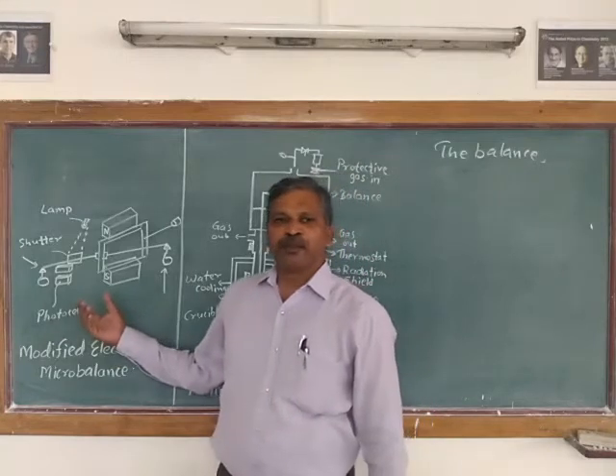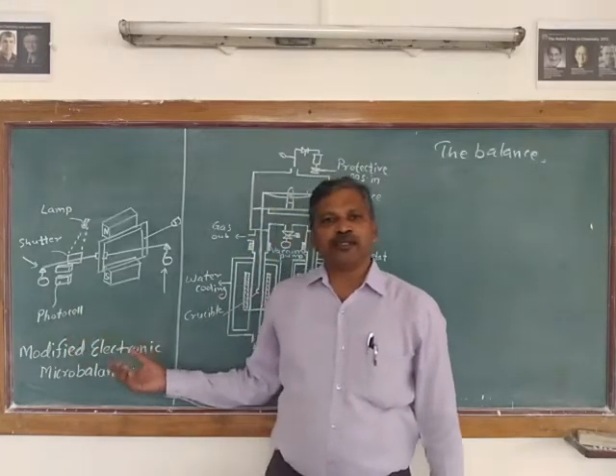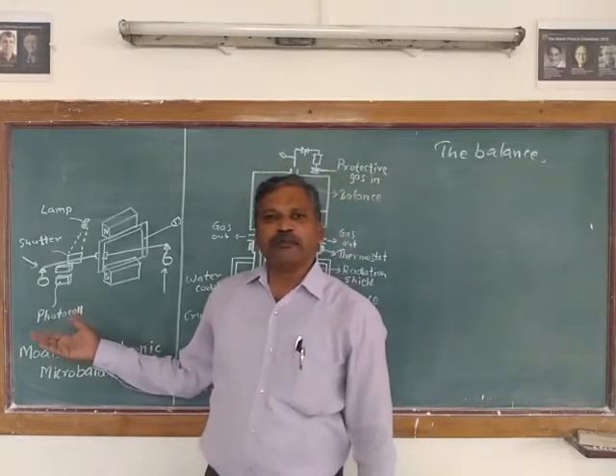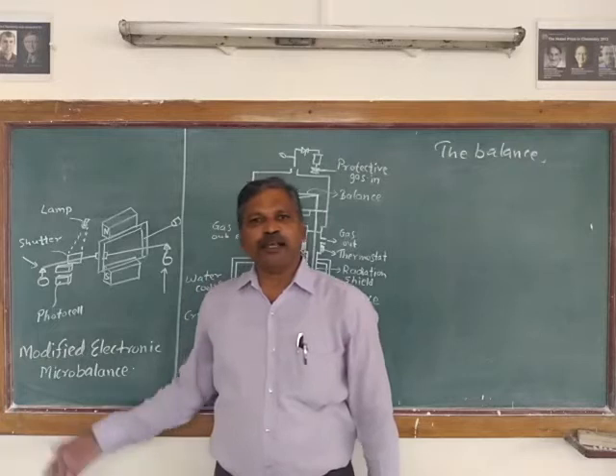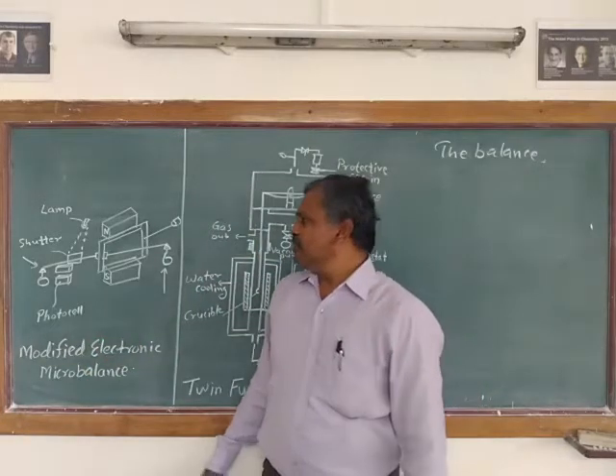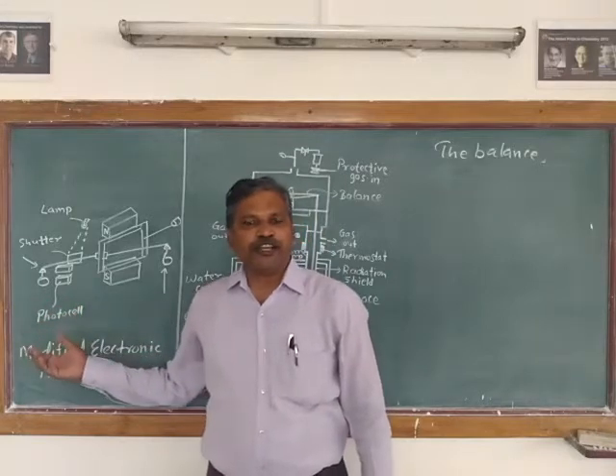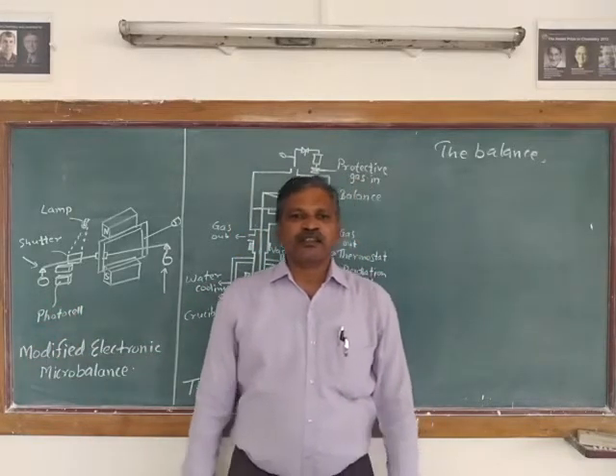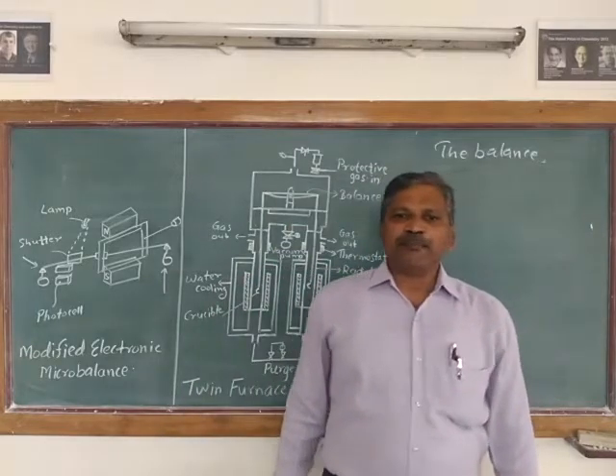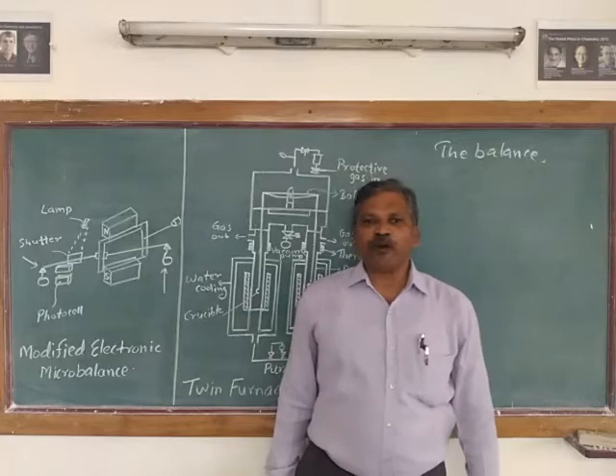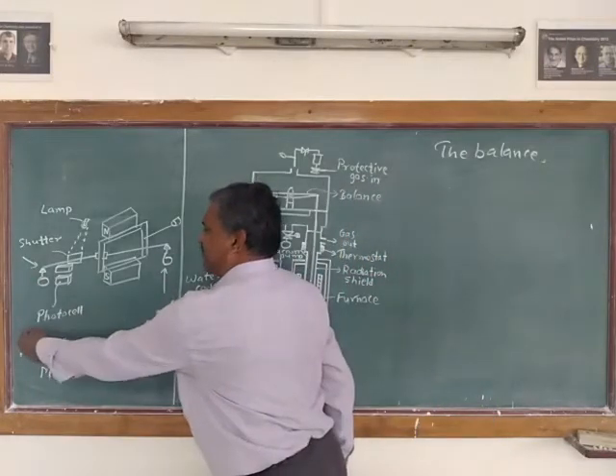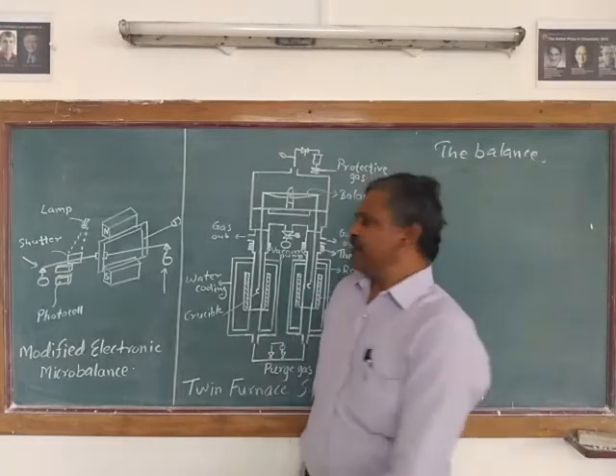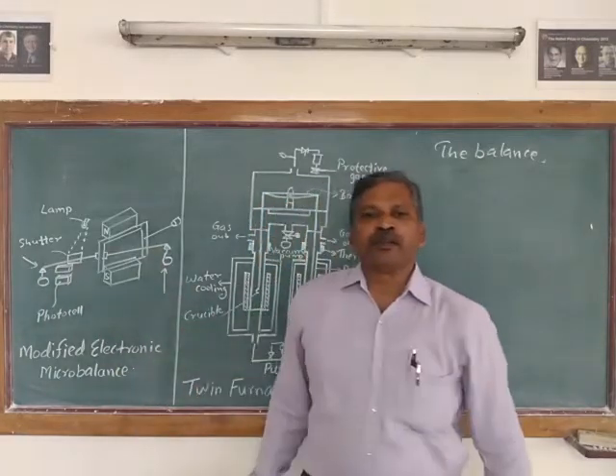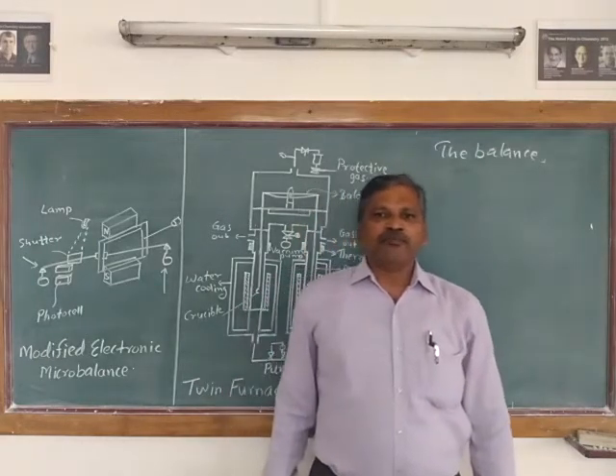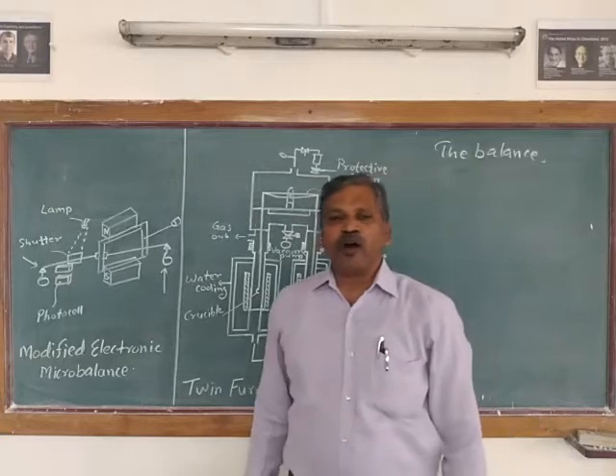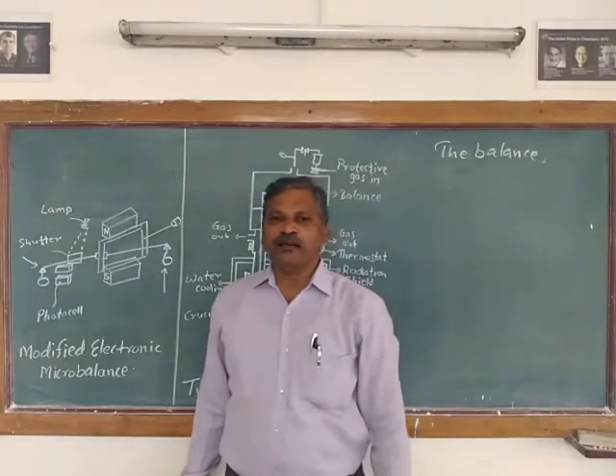When you heat the sample, some gases may evolve and the weight of the sample may get reduced, and therefore it may change its position in the furnace. So to maintain that position in the furnace, the loss in the weight of the sample is to be counterbalanced. The sample is suspended in the furnace from one arm of the balance. From here the sample is suspended and it is counterbalanced by the tare, either by an electrically applied field to the coil or by adding some reference weight in the pan.